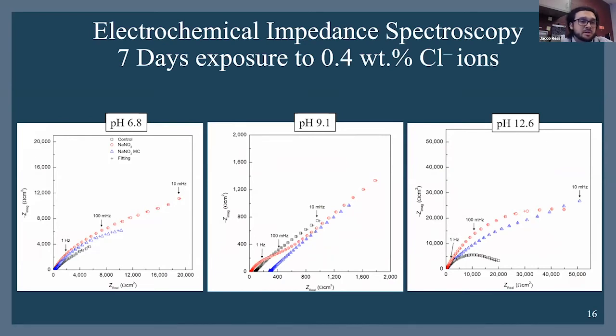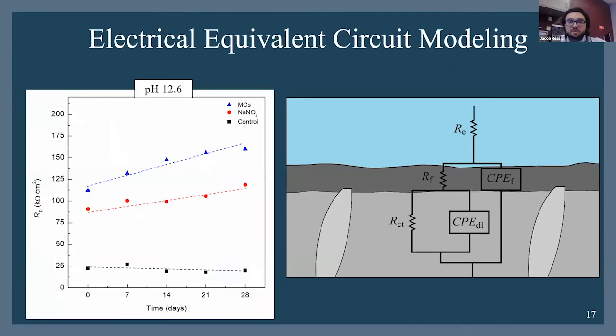We see that in the same color scheme, red being our free inhibitor, our free inhibitor samples show the most resistance for our 2 lower pH values. However, in our most alkaline, where we will have the most release of corrosion inhibitors, we then have the greatest impedance in blue here. These are all modeled to our electrical equivalent circuit shown here, widely used for inhibitors in concrete, with 2 time constants, one for our passive film formation of our oxyhydroxide and passive oxide layers, and our double layer and charge transfer.